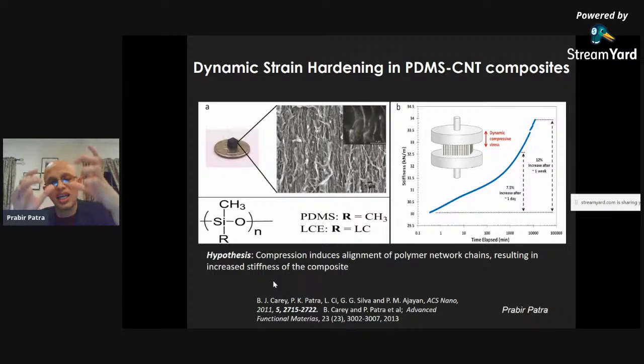What we did is form vertically aligned carbon nanotubes by a method known as CVD, chemical vapor deposition. On those aligned carbon nanotubes, which are very small, 10 nanometers in diameter, and equidistant apart, we put a polymer in oligomeric form and then polymerized it, and we formed a PDMS-CNT structure. Then we took the catalyst away and formed an open-ended composite, as you see on the coin. That black blob that you see is our composite. It has a unique behavior. We started giving a dynamic compression, and these are published in detail. If you want to know more details, these publications are there; anybody can look them up. But to cut the long story short, with these composites, the more compression you give, the stronger it gets. More stiffening happens in the structure. We call it dynamic strain hardening.